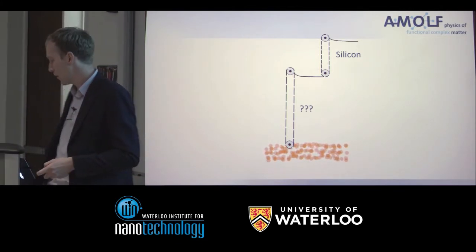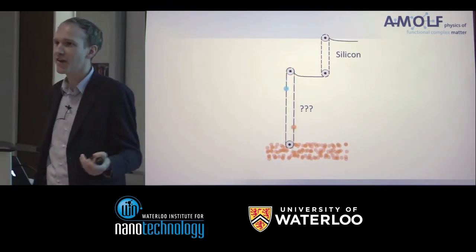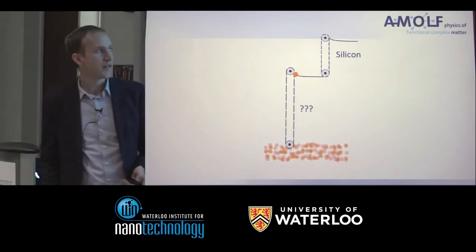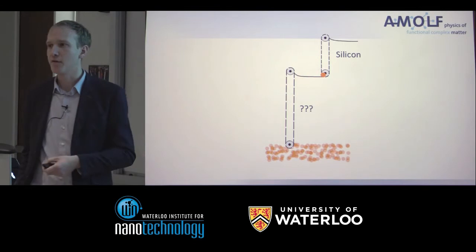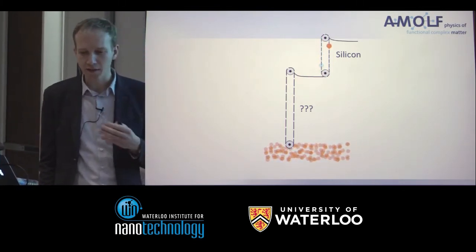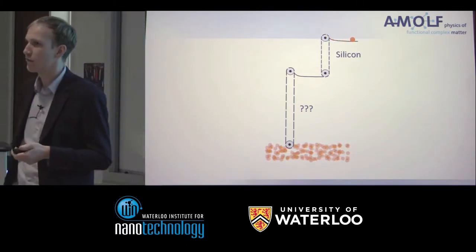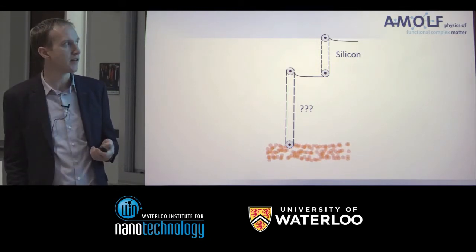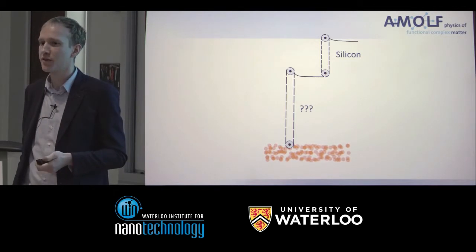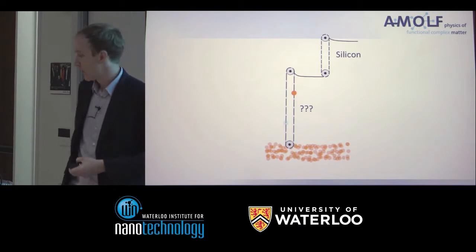Now, silicon is an excellent choice for the low bandgap semiconductor because silicon is really cheap these days. It's very well established, and there's huge factories for silicon. It's highly optimized. So the question is then, what do you use for the high bandgap semiconductor? And so far, people have mainly used things like gallium arsenide and indium gallium arsenide because they work very well. I mean, the latest efficiency record of gallium arsenide or indium gallium arsenide on silicon is, I think, about 33%, which is just above the Shockley-Queisser limit for silicon. The problem is that they're also very expensive to make. And recently,